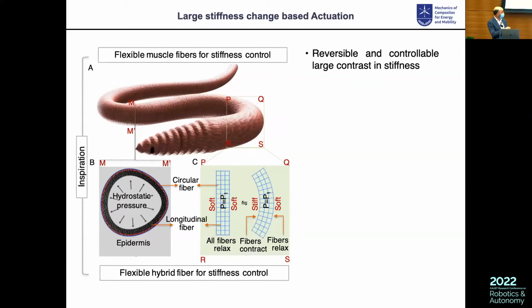That means doing exactly the same thing that you do in worms. You have a pocket under pressure. You make a hydrostatic pressure that is coming from your transition from liquid to gas. And then you need to be able to control the stiffness at every point of the membrane, and to change the stiffness at every point to make sure that you can change the actuation, right? This is also something that is extremely difficult to do because you need to be able to have locally a change in stiffness.